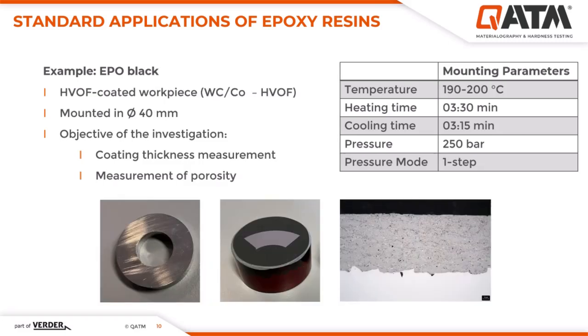Here is another example related to epoxy resin, focusing on the analysis of a martensitic steel that was coated with a tungsten carbide cobalt layer using high-velocity flame spraying to improve the wear resistance and the temperature stability of the material. Usually, this sprayed layer is analyzed in cross-section, measuring both the coating thickness and the porosity to assess the quality of the coating.